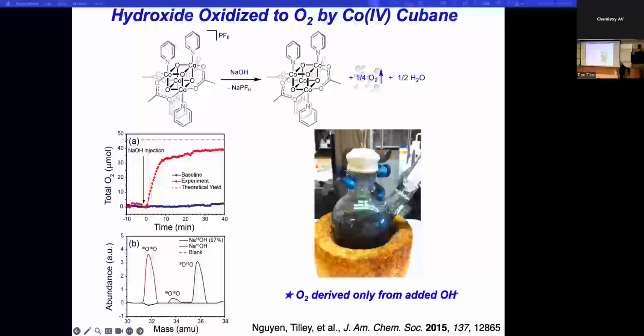And this is then a simpler reaction to deconvolute. One of the first things we did is O18 labeling. And this is the first surprise that we saw in looking into the mechanism of the species, which is that the O18 added in the sodium hydroxide all ends up in the O2. In other words, the oxos in this cluster do not participate in making the OO bond. I think this was a surprise, not only to us, but everybody else who'd been working with these kind of clusters in the context of oxygen evolution.